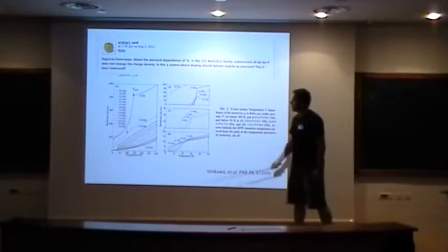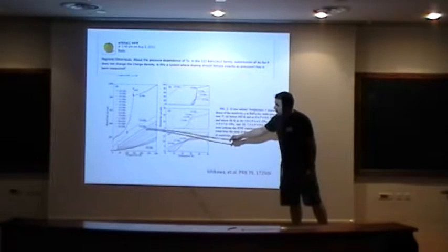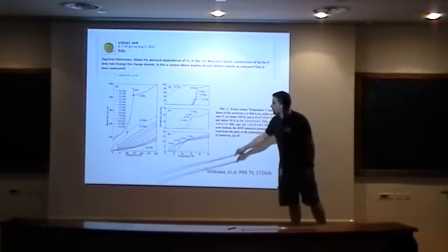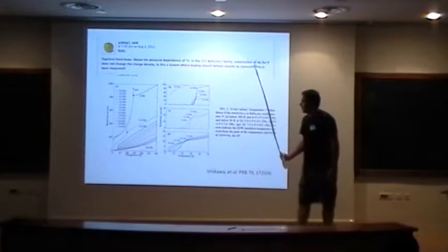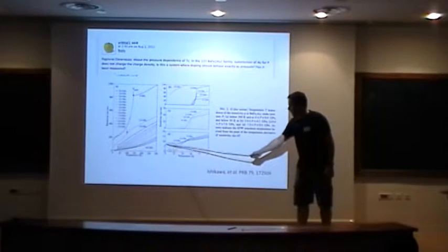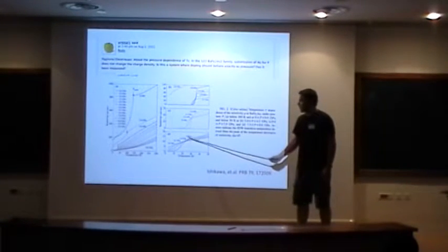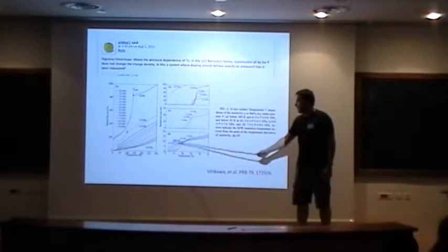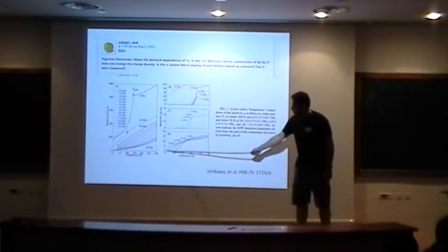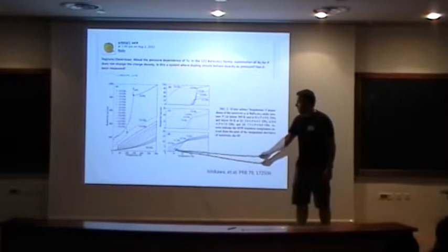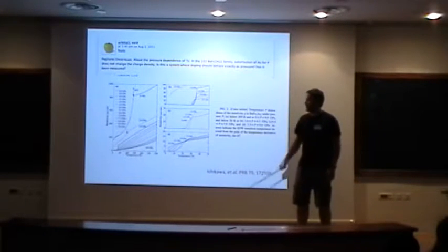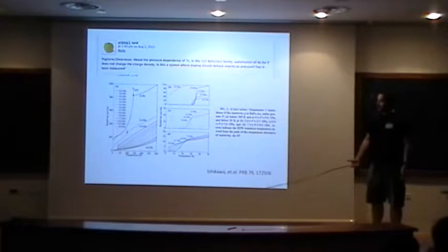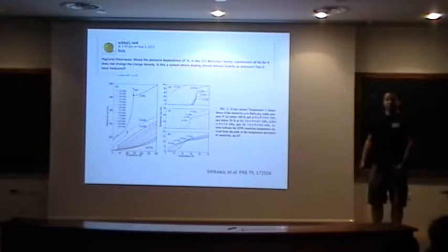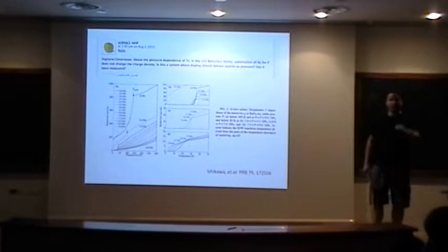And what they see is, as they apply pressure, superconductivity sets in. If they keep raising the pressure, superconductivity fades back out. So above 7.5 gigapascal, maybe at 8 there are still small signs of superconductivity, but afterwards it vanishes. Which sort of behaves like the superconducting dome in barium iron arsenide phosphide. When you dope it, first superconductivity sets in, and then it fades back out.